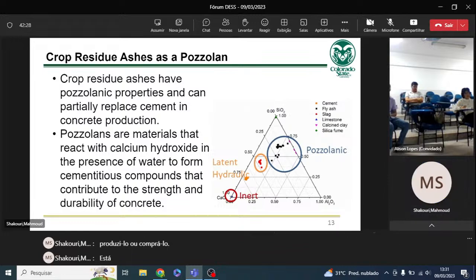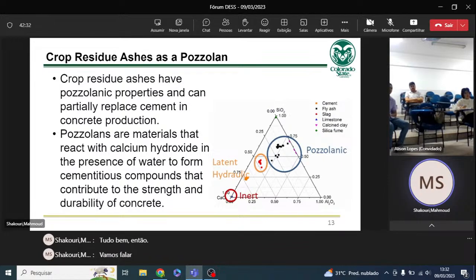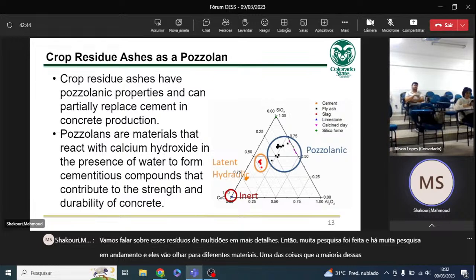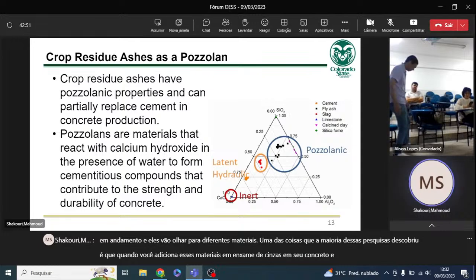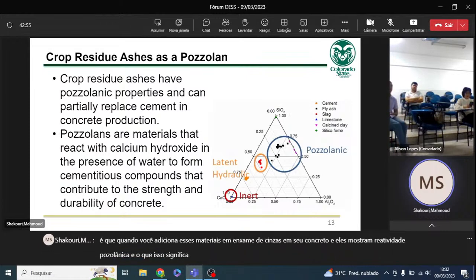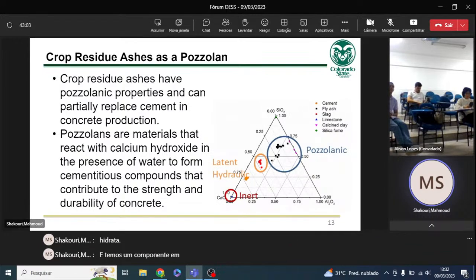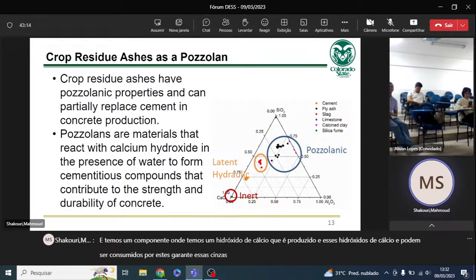All right, so let's talk about these crop residuals in more detail. A lot of research has been done, and there is a lot of research ongoing, and they look at different materials. One of the things that most of these studies have found is that when you add these materials in the form of ash into your concrete, they show pozzolanic reactivity. What it means is that during the cement hydration, when you add cement and water, it hydrates. And we have a component where calcium hydroxide is produced. And this calcium hydroxide can be consumed by these residual ashes, and they can produce calcium silicate hydrate, which is the building block of concrete. Calcium silicate hydrate is what gives concrete its strength.